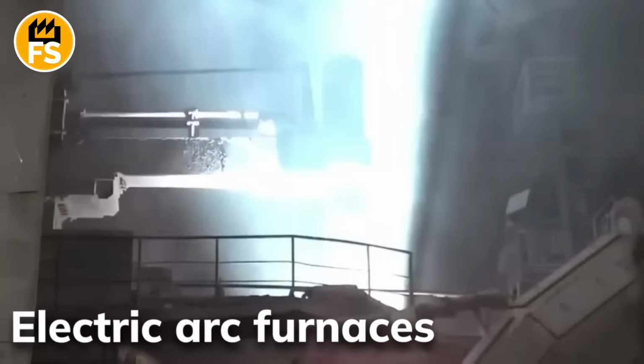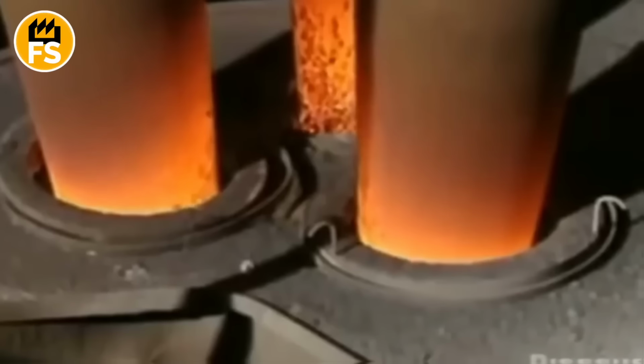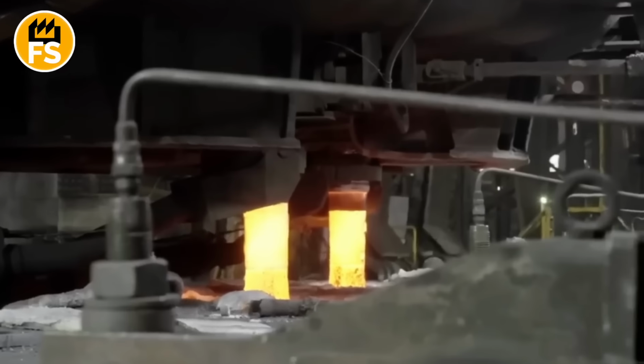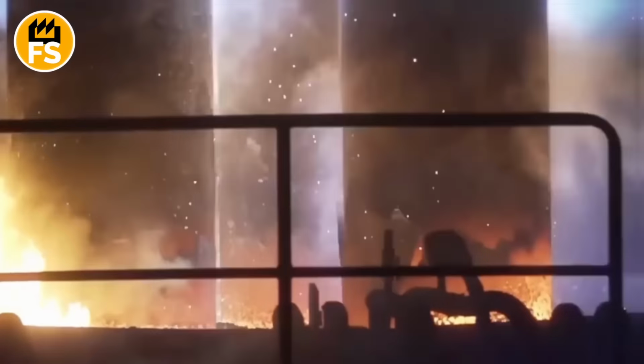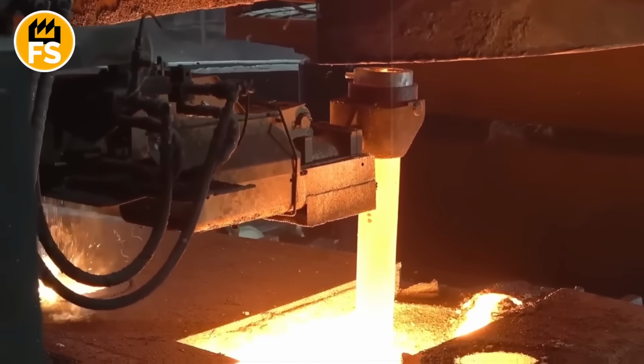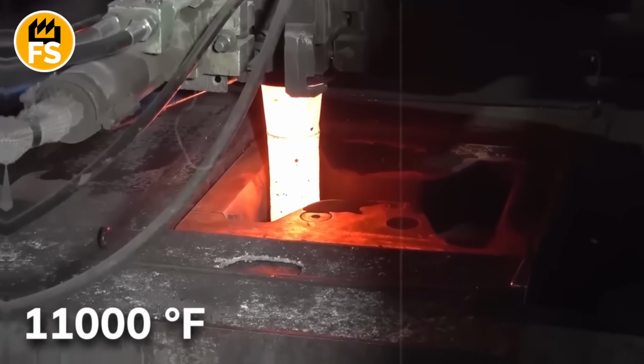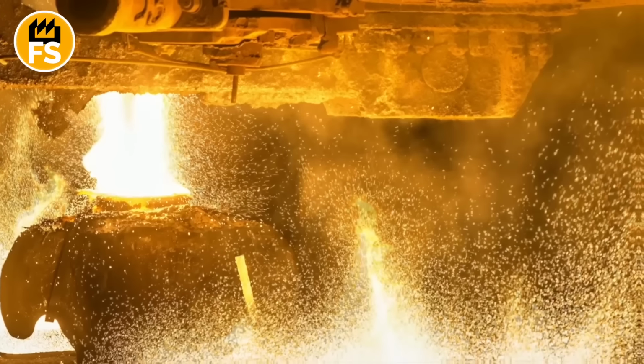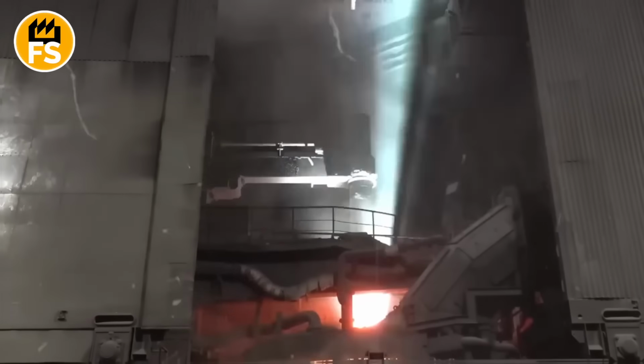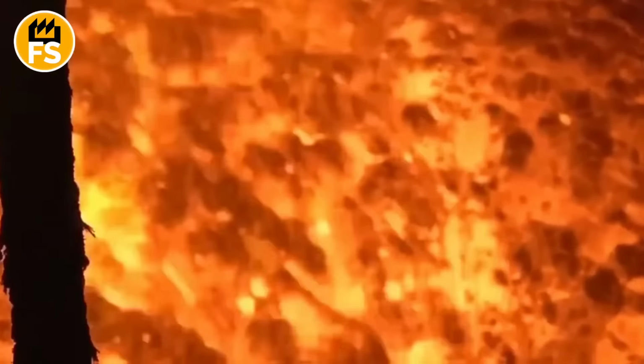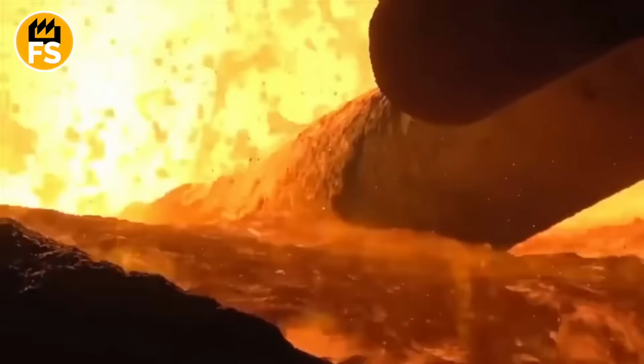Electric arc furnaces are used to melt down scrap metal. Massive graphite electrodes, up to 2 feet in diameter and several yards long, are lowered into the loaded scrap. An electric arc ignites between the electrodes and the metal, reaching temperatures up to 11,000 degrees Fahrenheit, hotter than the surface of the sun. Power consumption hits megawatts. A single furnace can burn through as much electricity as a small town. The metal melts, boils, violently reacts with added flux agents. Slag, a molten mix of oxides and silicates, floats to the surface of the metal and captures impurities. It's regularly tapped off separately.